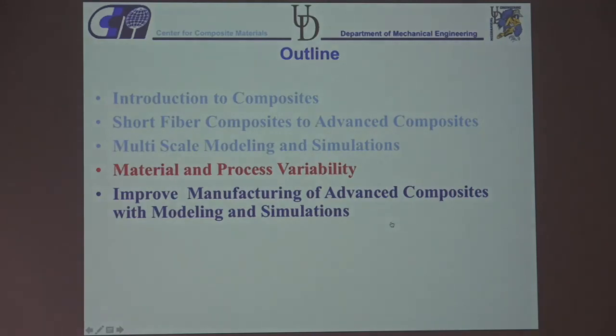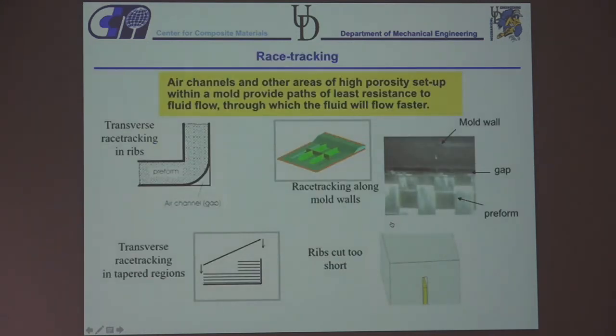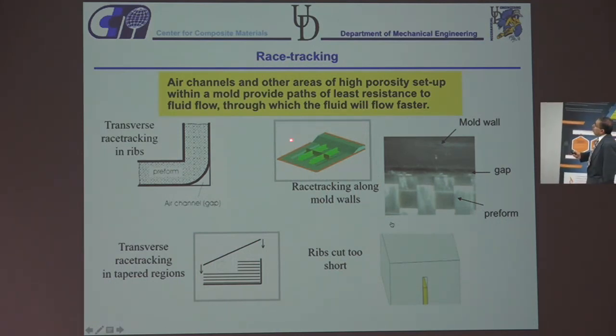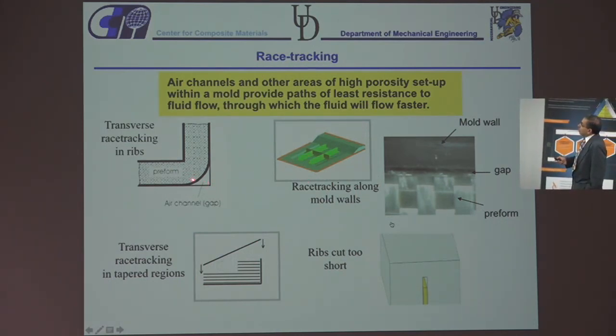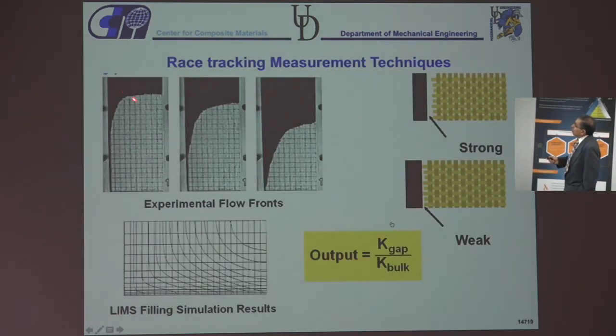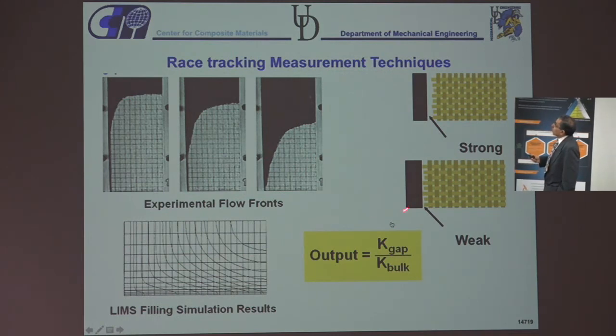Okay, so that was modeling at different levels. Now, how does material and process variability introduce more problems for us? So one very, very common process variability is race tracking. When you put the fabric along the walls, you will get some channels, you'll get some little areas here where it's not completely flush, so there will be a gap. You may have ribs that are cut too short, and all this will cause the flow to go faster in that region. And you can have either weak race tracking or strong race tracking.